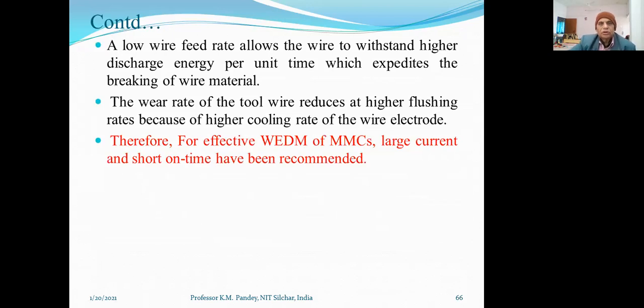So therefore, we have come to this conclusion that for effective WEDM of MMCs, large current and short on time have been recommended, because the wear rate of the tool wire reduces at higher flushing rates because of the higher cooling rate of the wire electrode, and a low wire feed rate allows the wire to withstand higher discharge energy per unit time, which expedites the breaking of the wire material.